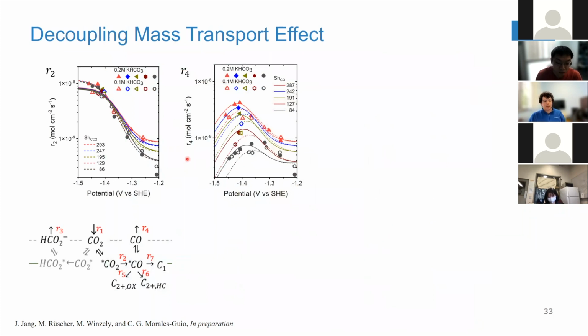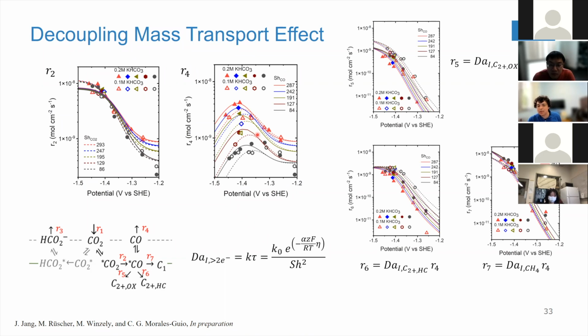And I will just finish by pointing out that all the points that you see here are experimental data points. It's the average of 3 different experiments, and all the lines actually come from a first principle model. So I showed you so far just the results at a fixed potential, different rotation rates, but you can also do different rotations and different potentials. And what you see is that the same first principle model actually can explain all the different production rates that you get. But again, all this is possible simply through the use of dimensionless Damköhler numbers and the relative relations between processes that are happening in this complex network.